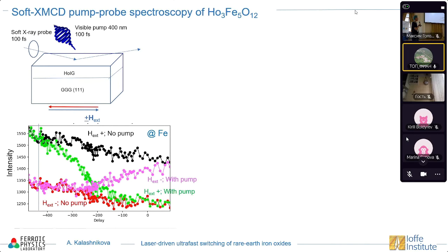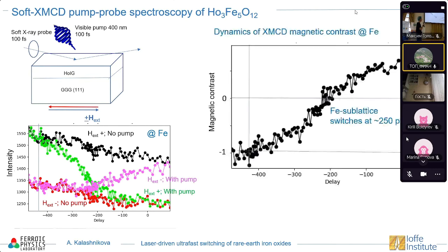The black and red curves are just intensity versus time delay when we have no pumping. There is some drift, but in general the contrast, which is the difference between these two curves, doesn't change. So no pumping, nothing changes. If we switch on the pump, we look at the green and magenta curves, and we see that the contrast between them starts to change, goes to 0, and switches. We can subtract them and plot it here as magnetic contrast. We go from -1, we switch at something like 250 picoseconds, and then we really see reversed contrast. So this is laser-driven switching via the compensation point, most probably.